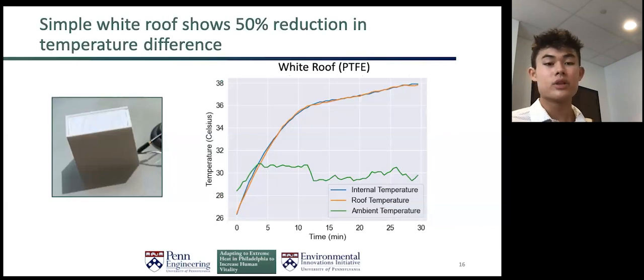So I used a white Teflon coating instead of the black PVC coating, and the roof only reached 38 degrees Celsius. So it was about 8 degrees over the ambient temperature. And that's more than a 50% reduction from the 20-degree difference for the black roof. One weird feature of this graph is that the internal temperature and the roof temperature are about the same the entire time, which really isn't what I expected.